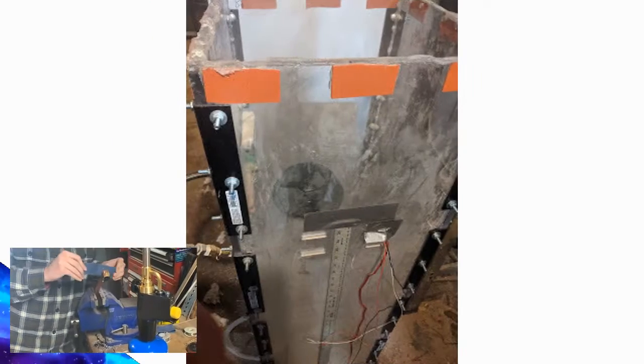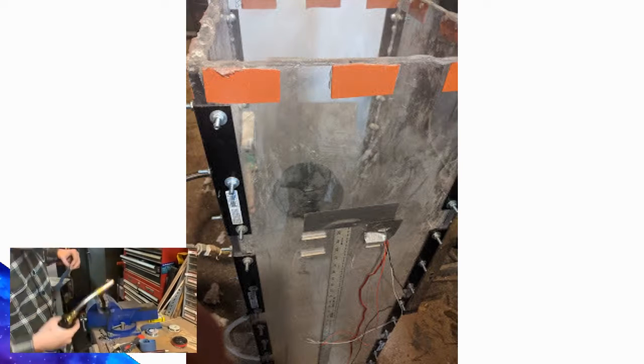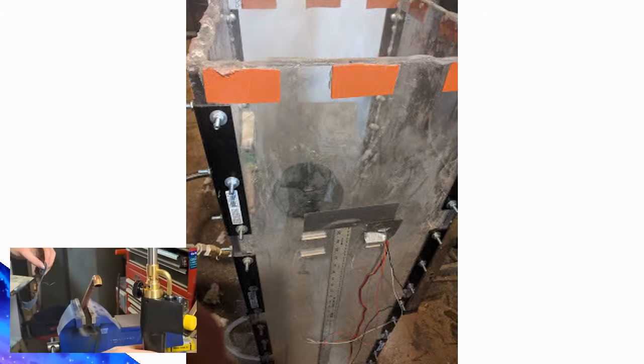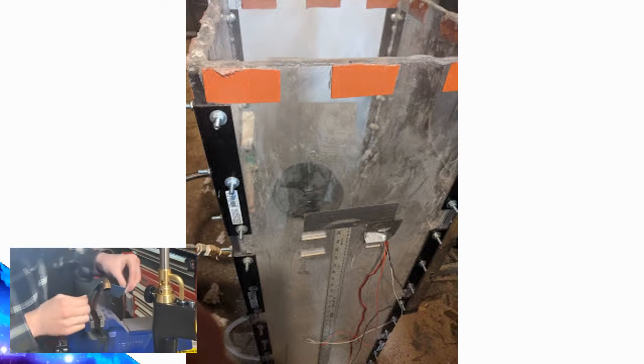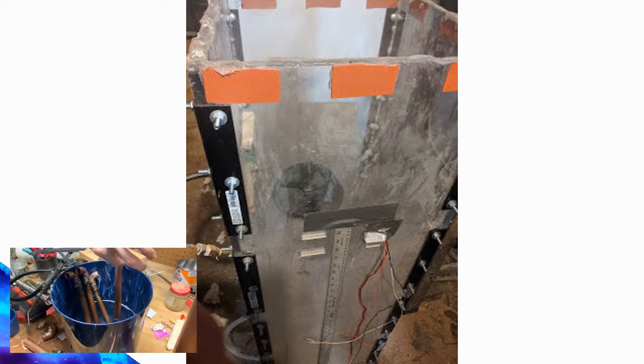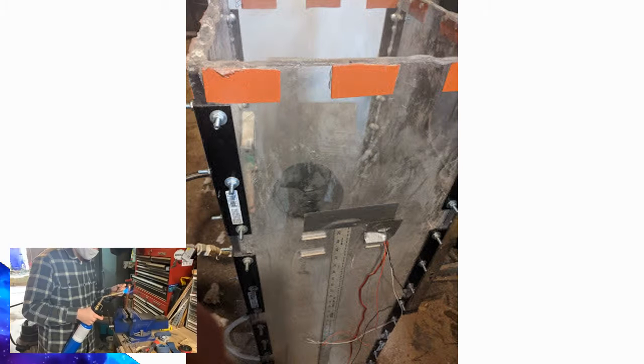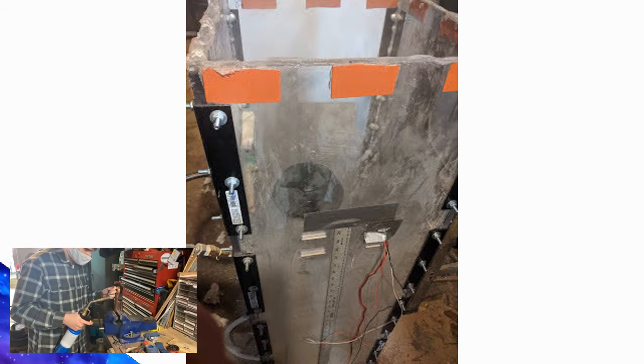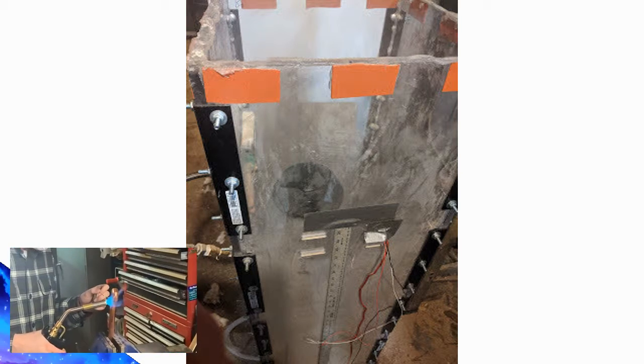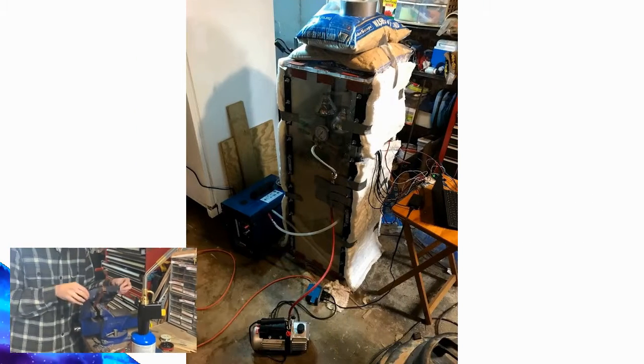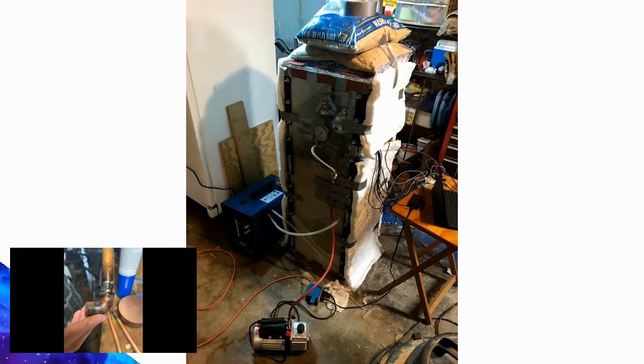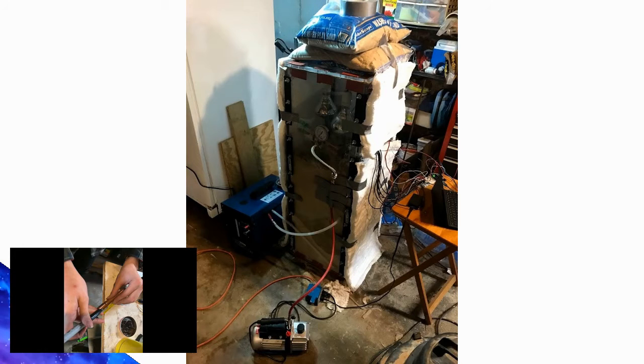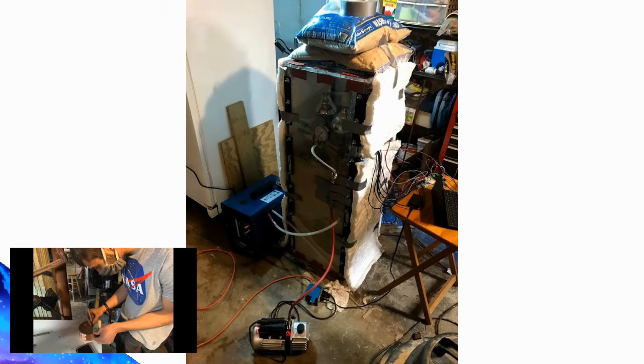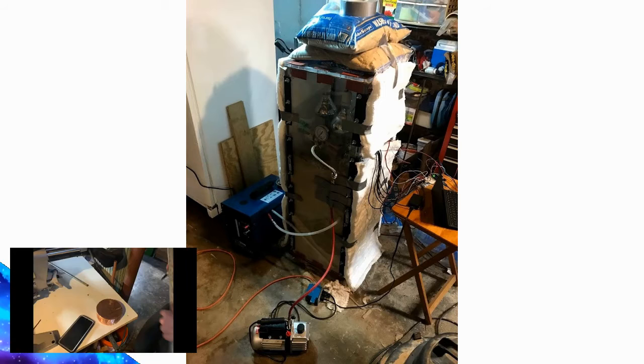Instead of the planned bolts on top and bottom of the box, a design change was made to make the top of the box easily removable for access to the experiment. The unused holes were sealed with rubber patches and a silicone ring was put on top of the vertical acrylic sheets. Atmospheric pressure pushing in on the rubber box top created an airtight seal. The box top also had the added weight of the sandbags pushing down to squash uneven parts of the silicone ring and create a seal. The vacuum chamber was not perfectly airtight, but it held a near vacuum with the air pump constantly running.